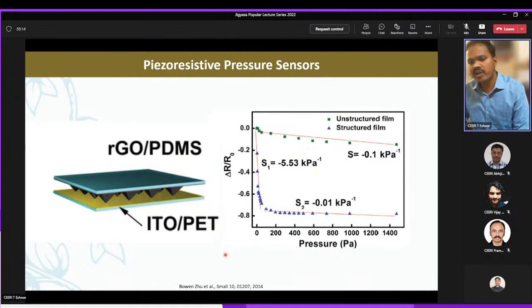For example, here is a simple example of one electrode, ITO on PET. This is a transparent electrode on which there is a micro pyramidal structure of PDMS. PDMS is polydimethylsiloxane, an elastomeric medium, over which reduced graphene oxide has been coated. Now, RGO is a resistive medium. When the electric contacts are taken from here and here, based on the contact area between these micropyramids and the bottom electrode, the resistance changes. For example, initially the resistance is here. With applied pressure, the change in resistance is shown here.